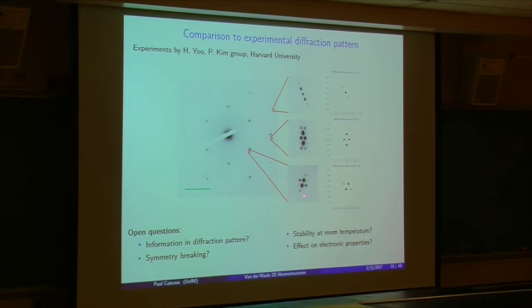But then I also see satellite peaks that come from the relaxation. And I can compare that to my prediction just by taking the Fourier transform of this pattern I was simulating earlier and see if I'm predicting something that looks reasonable. So here we see, for example, that we have the right peaks. The simulation seems to pick up at least the right peaks. However, over here, it's clear that the middle peak is not quite as strong in experiments as it is in the simulation, and therefore there is actually hope. So this is not a bad result. This is a result that tells me that there is information in the diffraction pattern that can be exploited to validate a model. My model was very rudimentary.